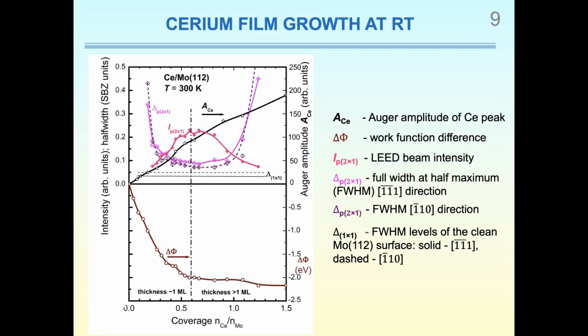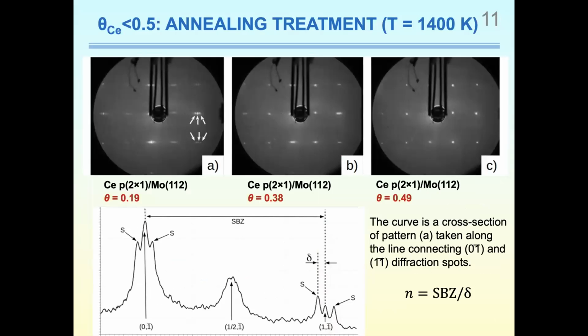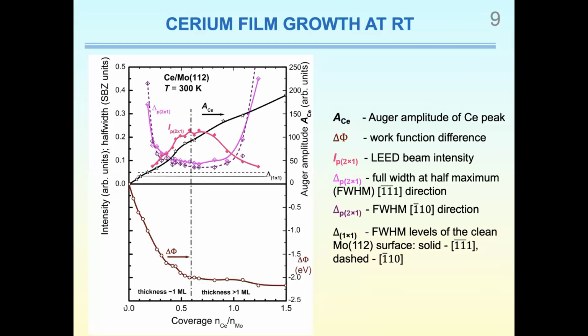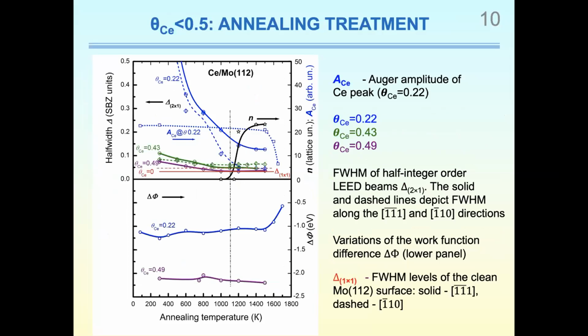However, the first primitive 2x1 monolayer is not perfectly ordered. Indeed, the half-width never reaches its possible ultimate minimum value, as well as its lowest attained value falls at coverages exceeding the stoichiometric value of 0.5. So here you can see that it does not reach the ultimate value. Obviously, the structure of the overlayer deposited at room temperature is not balanced enough and contains numerous defects, including possible oxygen impurities. Okay, let's go forward.